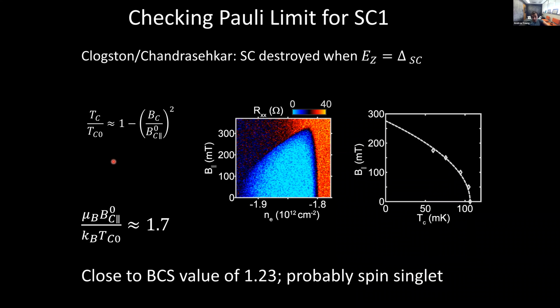We can check other aspects of what you expect for simple superconductors. So for example, in a spin singlet superconductor, you expect superconductivity to be destroyed when the Zeeman energy becomes comparable to the superconducting gap, because that's basically pair breaking. And within BCS, the ratio of that Zeeman energy to k_B times the zero magnetic field transition temperature is something on the order of 2.